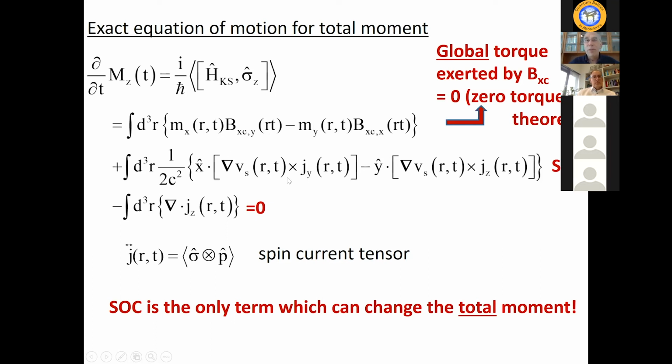Now, this is spin-orbit coupling. It changes the direction in a complicated way. One thing that you can actually prove from the equation, which is complicated, is that at the initial point in time, at the time you switch on the laser, in the first moments from the initial ground state, this always leads to a decrease of the magnetization. What happens later, we don't know, all kinds of things can happen, but initially you always decrease. That follows from this term here. That's another interesting aspect.